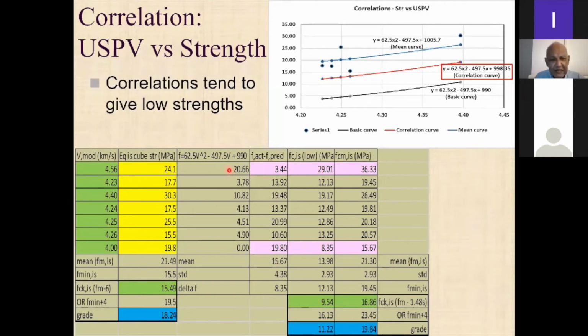So we take these, right, and we convert the strength to this using this equation that is given in the Eurocode, right? Then this will actually give the predicted strengths using this basic curve. That's a basic curve, right? Now, the actual strengths are these, right? So you take F actual minus F predict. These are almost all positive, right? Because this curve tends to give you low strengths, right? So then you take the mean of that, which is 15.67, right?